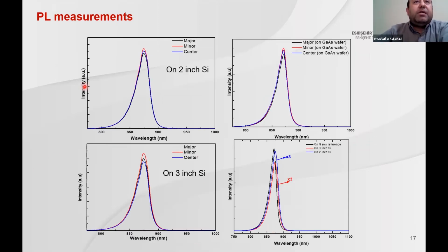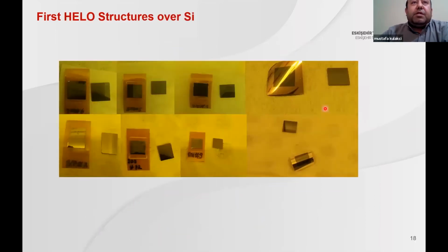When you look at the PL results, here you can easily see the efficient PL emission from the devices over silicon. And when you compare with gallium arsenide, of course, it is a bit lower compared to the gallium arsenide reference, but maybe in a week, we are going to almost reach the gallium arsenide reference case here. Of course, these are the first solar cell structures transferred directly from silicon in the world, to our knowledge, and it is first announced also here.